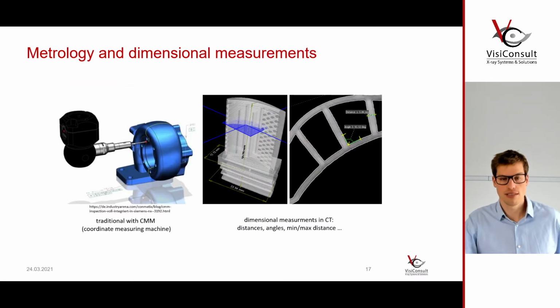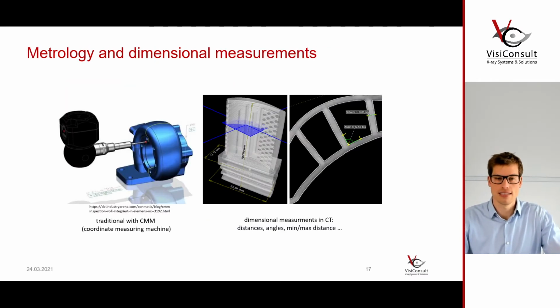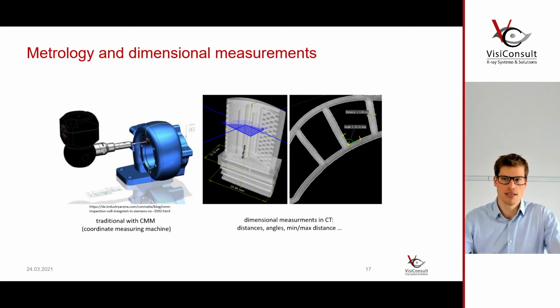What you also can do with CT, it's not ending yet, is that you can perform metrology jobs. Obviously, CT systems are no CMM systems, which means you will most likely get a better resolution, accuracy, measurement, tolerance on a real calibrated perfect CMM. But you can get close enough with CT. You can get down to single-digit micron measurement resolutions. And the biggest advantage is that you can measure channels on the inside and structures on the inside.